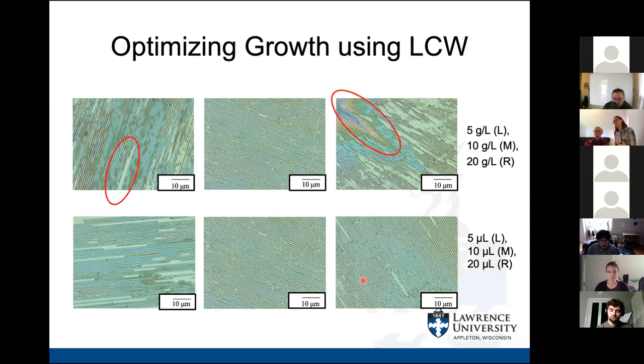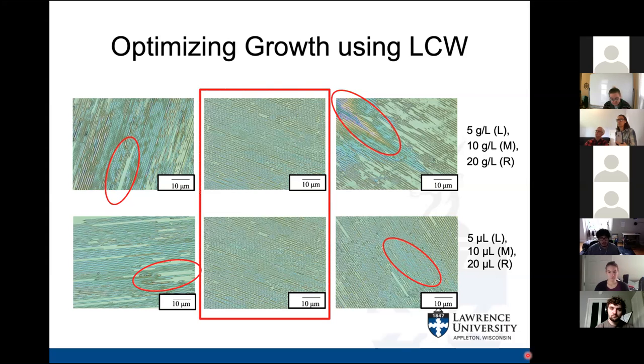Again, after imaging with a scanning laser microscope, it seems that 10 microliters was the most ideal drop size, since 5 microliters produced inconsistent growth and 20 microliters was overgrown in places. Although some substrates showed under and overgrowth in all concentrations, after repeating this test many times, it seems that 10 grams per liter and 10 microliters were the parameters that caused the most consistent crystal growth. So overall, the most ideal conditions to produce good crystal growth were 10 grams per liter and 10 microliters.